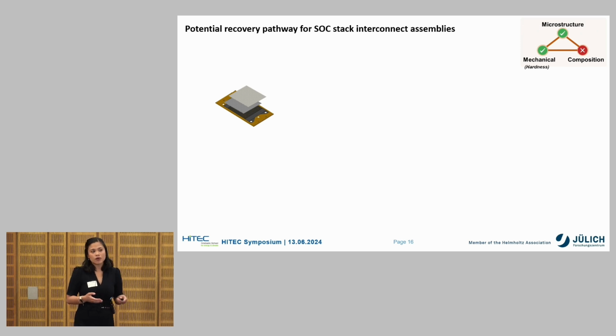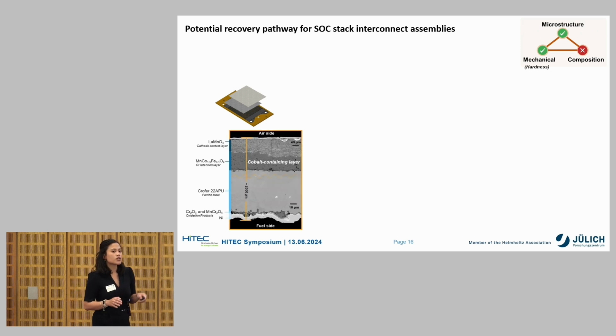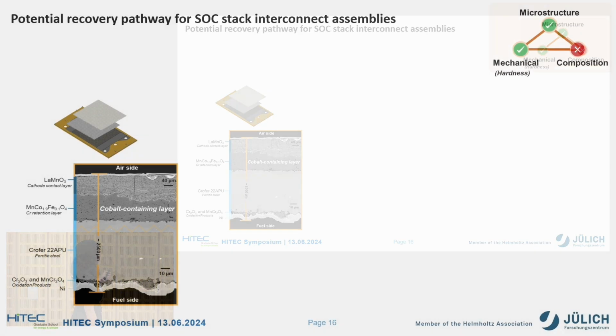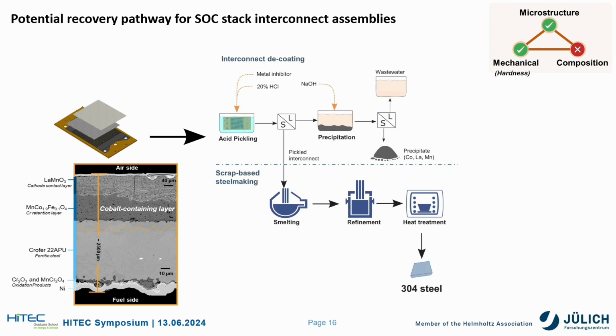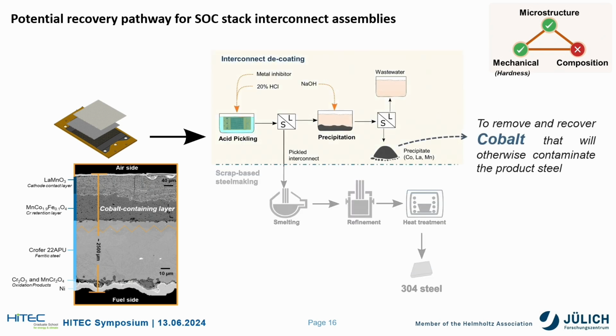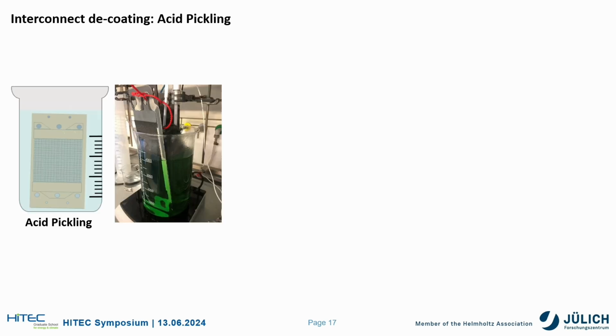The good thing about our sample is that cobalt is concentrated on the coating layers, specifically on this MCF coating here. Hence, we can add some interconnect decoating steps in order to remove and recover cobalt and other coating elements that would otherwise contaminate our product steel. These decoating steps are constituted of acid pickling and precipitation. Due to time constraints, I have to focus only on the results from acid pickling tests.